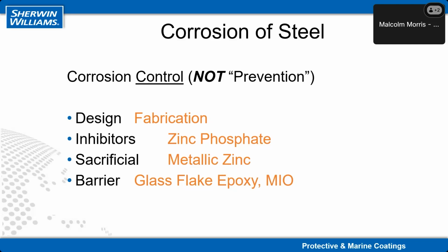Sacrificial paints, metallic zinc can be incorporated into primers to form what we call zinc-rich primers, and the zinc there acts as a false anode and will actually corrode preferentially to the steel in a corrosion situation. So they are very effective corrosion protection primers. And also barrier coatings. As I say, if you can eliminate that electrolyte or outside environment from the steel to stop water and oxygen getting to the steel, then you will greatly reduce the rate at which corrosion occurs. And we use pigments like glass flake, MIOs, micaceous iron oxide. So these pigments will give a very good overlapping barrier effect within the coating.